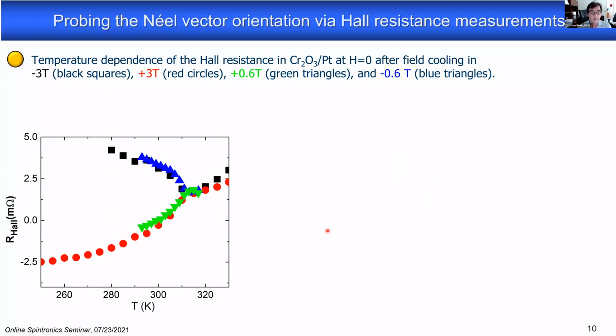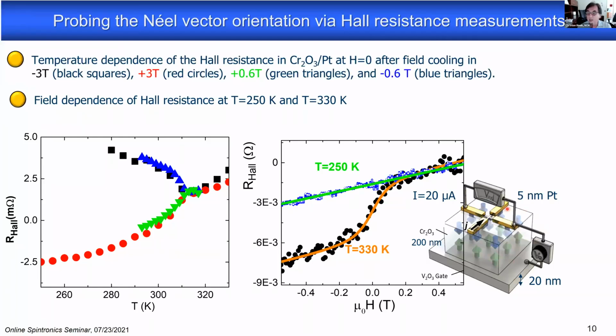So first, I want to show you data. In this case, I show you our data measured on pure chromia. But there are other data, for example, from the group in Dresden, Kosub and others, who did the exact same type of experiments and came to the exact same conclusions. So if you have a system like this, you have your chromia thin film, you deposit a Hall bar of a heavy metal on top, platinum in this case, and you drive a current through it and you pick up the transverse voltage, a Hall-like signal.